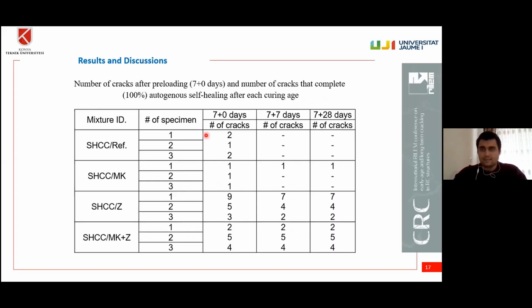As I said, we also assessed the crack widths and crack numbers. Here, we can see that zeolite bearing specimens underwent a very high number of multiple microcracks. This was because of the rheology of zeolite, because in these strain hardening cementitious composites, we are trying to tailor the friction behavior of matrix and fiber. These zeolite particles probably reduced the toughness of the matrix and therefore gave a highly ductile behavior, and accordingly we obtained a higher number of cracks with smaller crack widths.